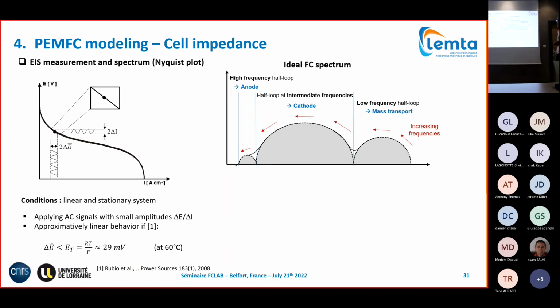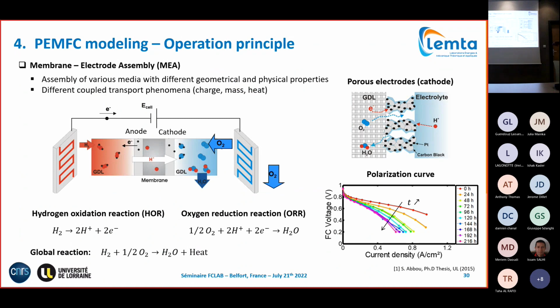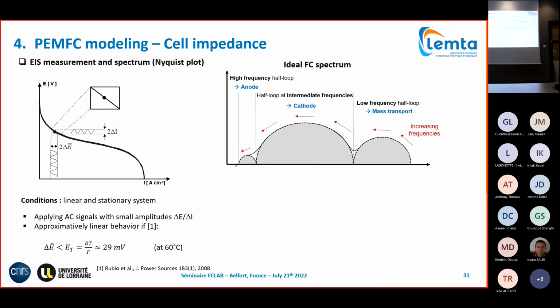When we measure the impedance of a fuel cell, we apply a current perturbation at a given imposed current and measure the corresponding response in terms of voltage perturbation. Ideally, the spectrum will be composed of three loops. At the highest frequency, a very small loop is the anode, because the hydrogen oxidation reaction is very fast compared to the oxygen reduction reaction. At intermediate frequencies, the loop is associated with the cathode reaction kinetics, so the reduction of oxygen.